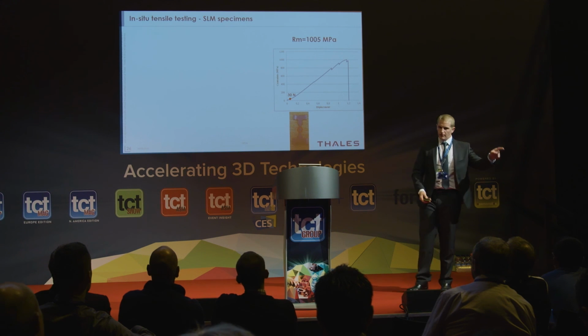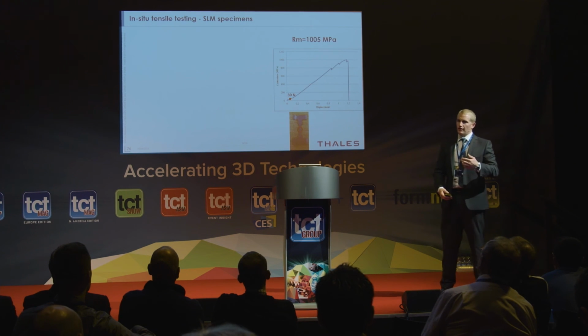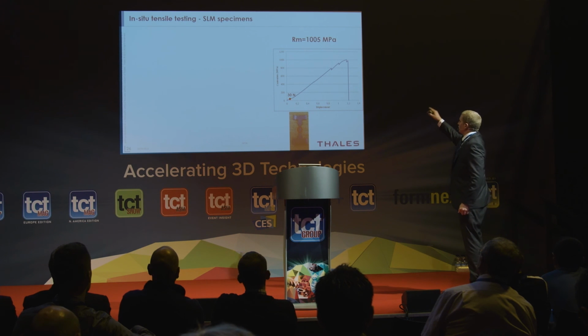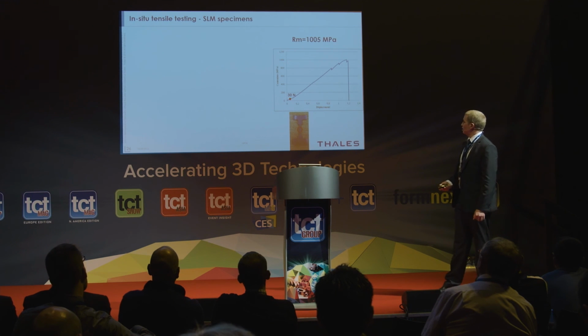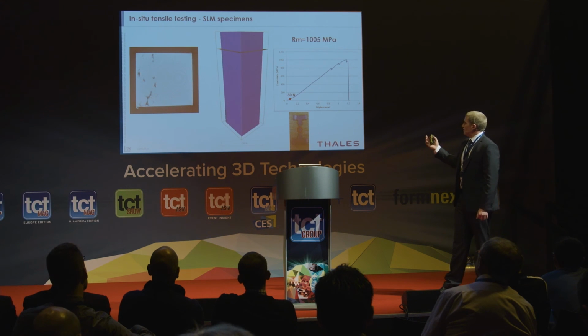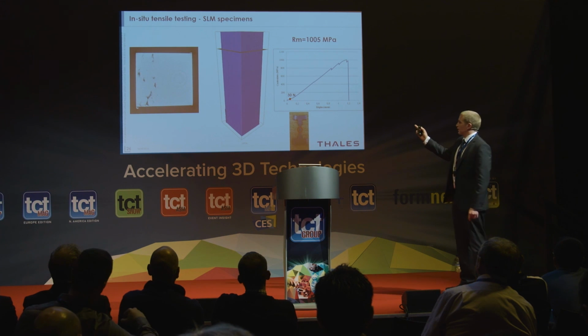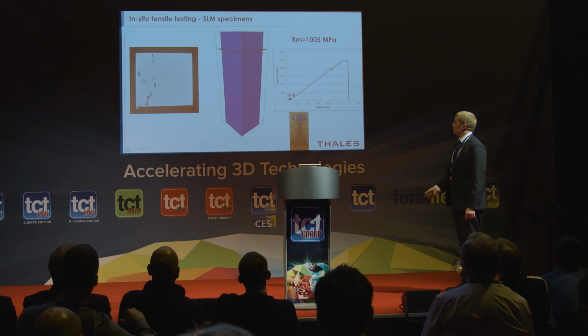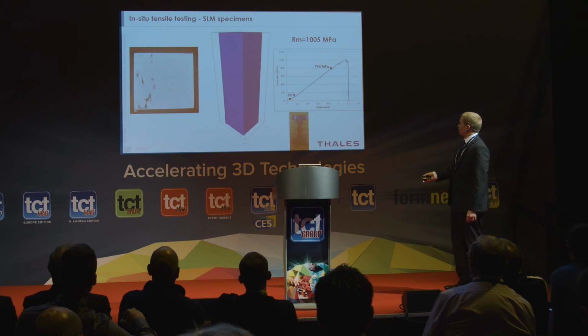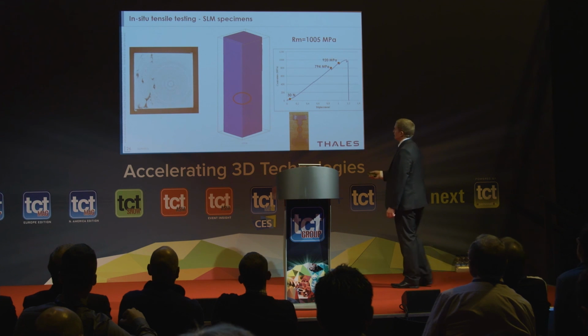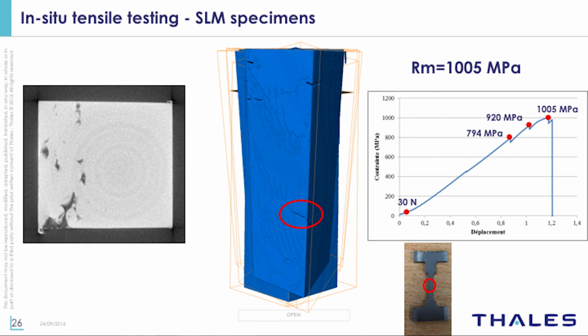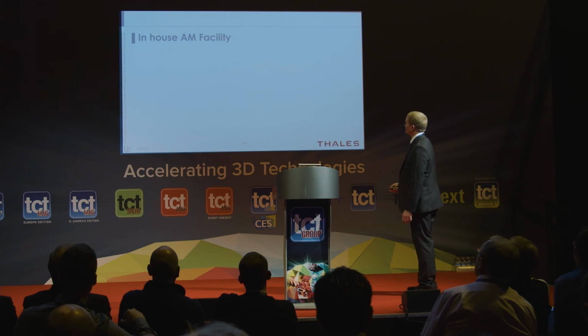So during our tensile test, you'd hear some pings or some clicks, and that would correspond to a drop in the curve on the right. So this is a scan of the cross-section of our test sample, the red circle in the bottom right. And as we go through, we can start to see these defects start to appear. So if we jump between these slides, you can see the cracks start to appear in here, which is quite a good indication of where some of these defects were coming from. It was just a nice thing to see from my side of things.